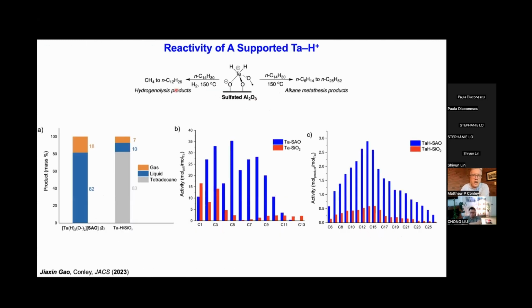When we do hydrogenolysis reactions with tetradecane, which we use as an alkane surrogate for polyethylene, we can see immediately that we have much greater reactivity for the tantalum hydride on sulfated alumina in hydrogenolysis reactions. So this is after 2 hours at 150 degrees. We fully convert all of the tetradecane to a distribution of alkanes, some of which are gases, most of which are liquids. If we let this run at longer times or at higher loadings, this all goes to methane, which is exactly what you expect for these types of metal hydrides.